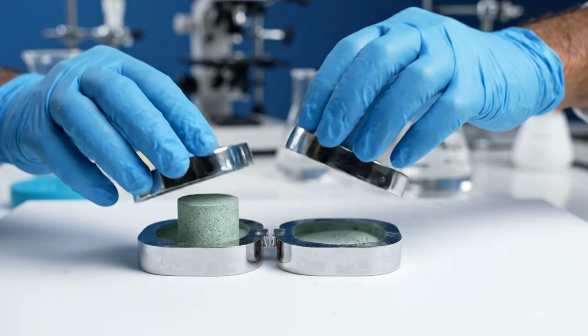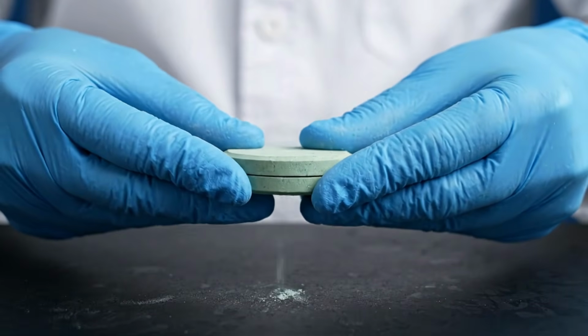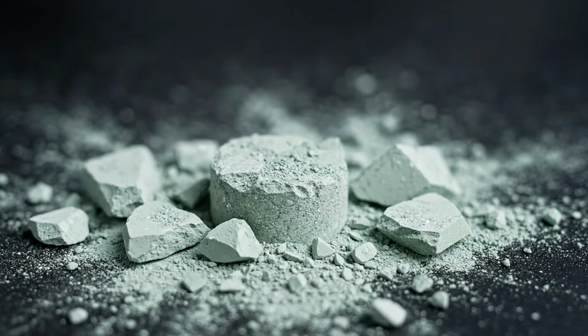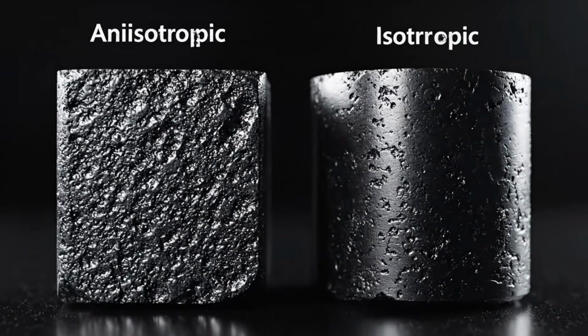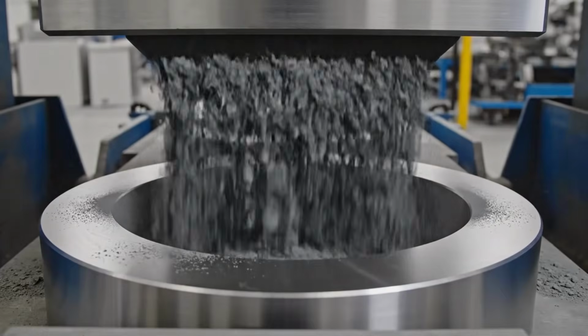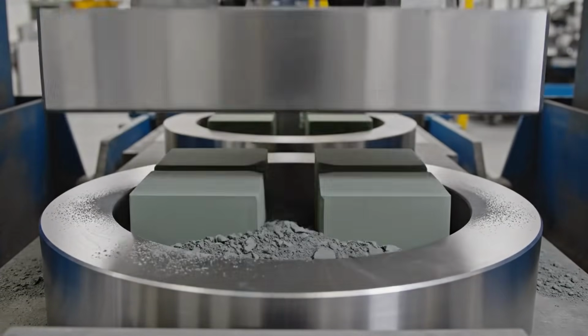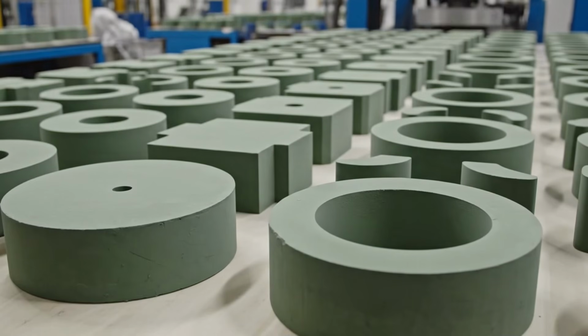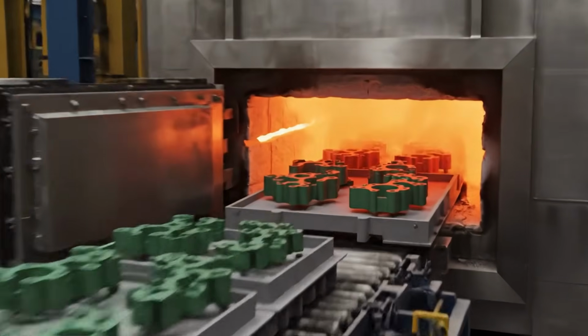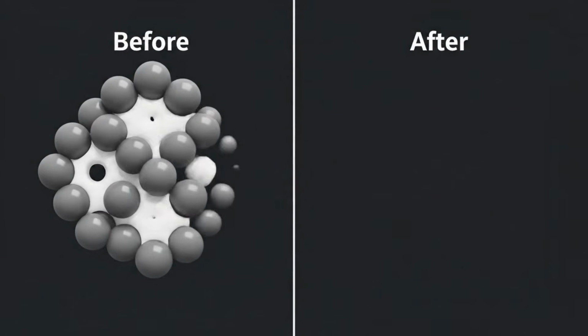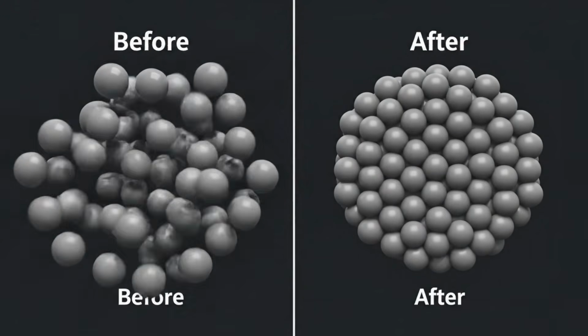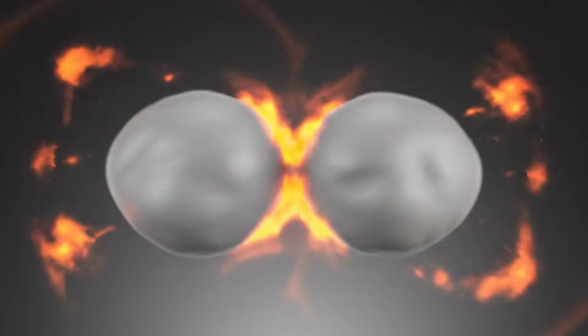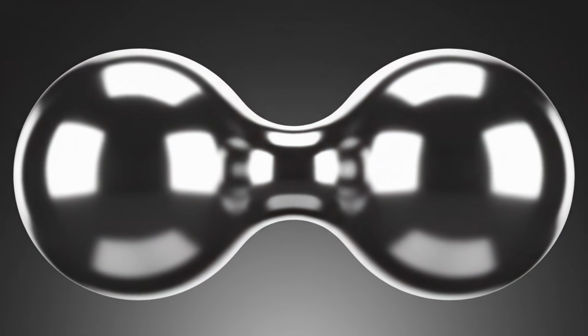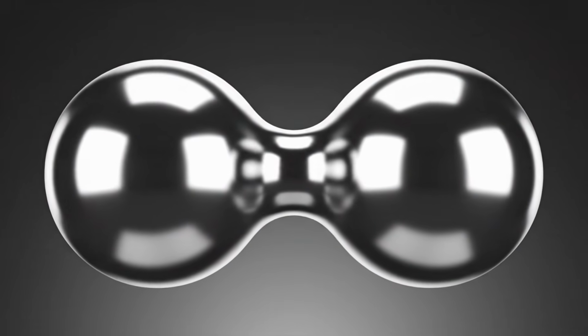The coating process depends on the end use. For general applications, electrolytic nickel plating can be used. The parts are cleaned, chemically activated, and immersed in baths where an electric current deposits a uniform metallic layer onto the surface. For humid environments or applications requiring electrical insulation, epoxy can be applied. In other cases, coatings more resistant to temperature or salt spray are used. Each layer must cover corners, edges, and cavities without leaving any pores. A microscopic defect can become a point of corrosion. After coating, the parts are inspected visually and dimensionally. The layer thickness is measured, adhesion is checked, and parts with cracks, chips, or scratches are discarded.